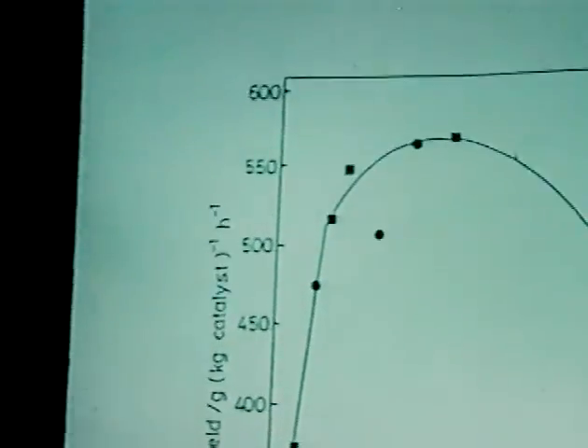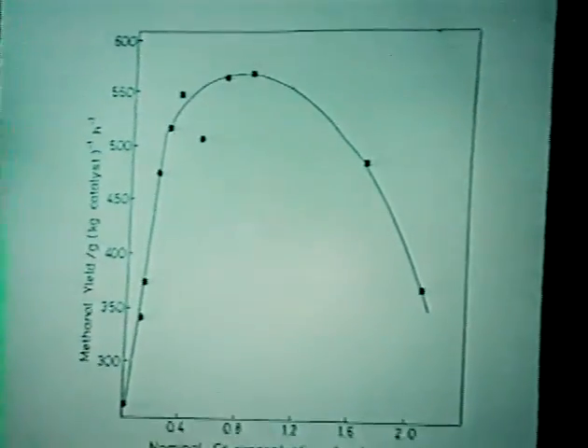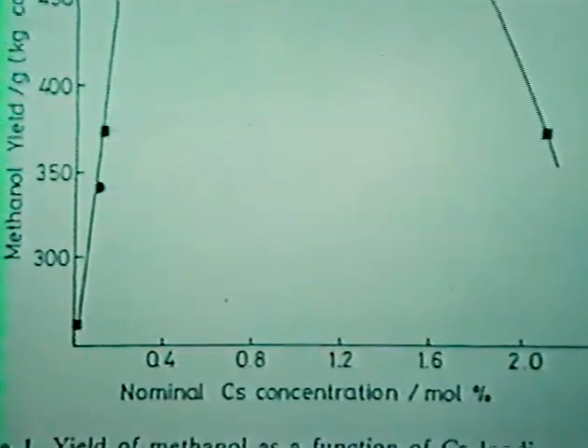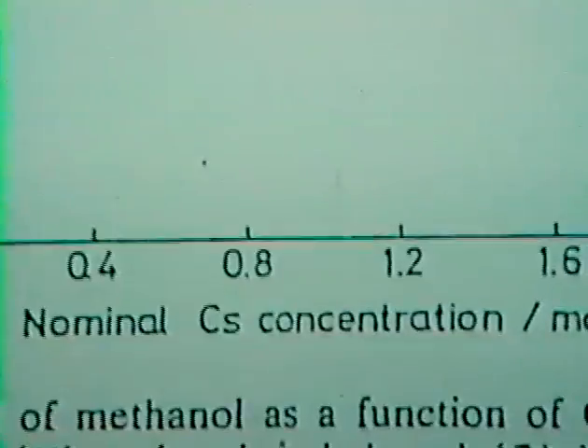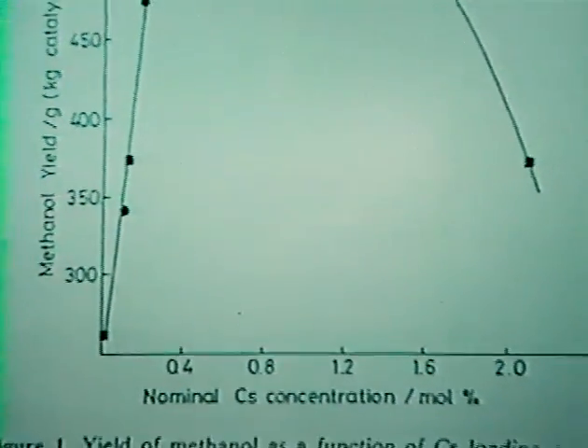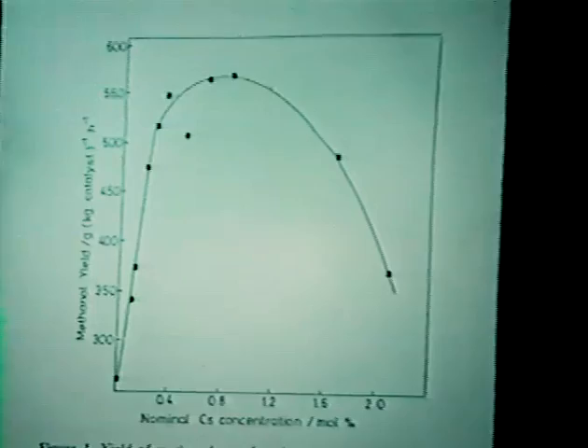The copper zinc oxide part forms the hydrogenation component, and we therefore have a bifunctional catalyst in which we have a basic function, that the cesium, the counterion of which the hydroxyl group provides, for a nucleophilic attack on carbon monoxide and formate formation. And then we have an activation of hydrogen on the copper zinc oxide part, which then hydrogenates to methanol.